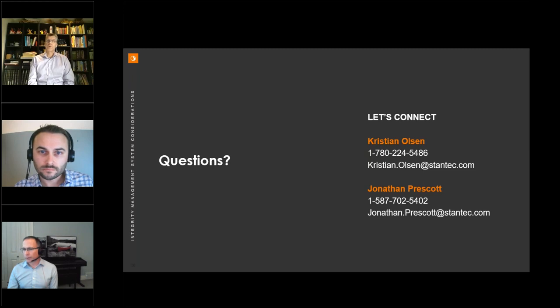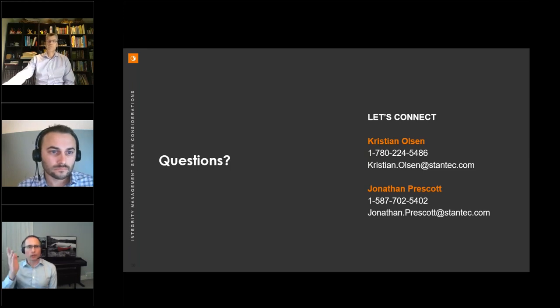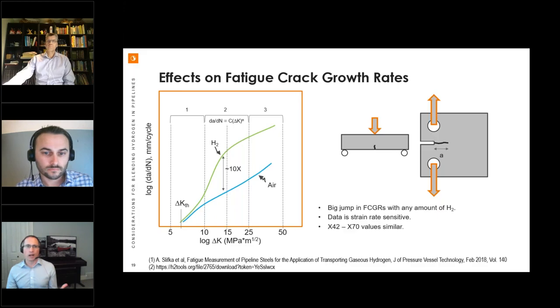Going off memory, within H2 tools, there's a write-up from Sandia National Labs. They take a lot of data, and there's a particular chart in there where they're showing, was it 0.02 MPa hydrogen? What was slide 19? What was that graph all about, Kristian? It's the effects on fatigue crack growth rates. I think the question is really about if we have a small amount of hydrogen, how small before we start to see this big leap? Within that reference, you'll see a table of carbon steel compatibility, and they show a line in air and then lines with various amounts of hydrogen in carbon steels. I believe it was 0.02 MPa hydrogen where they saw a big jump in the fatigue crack growth rates.